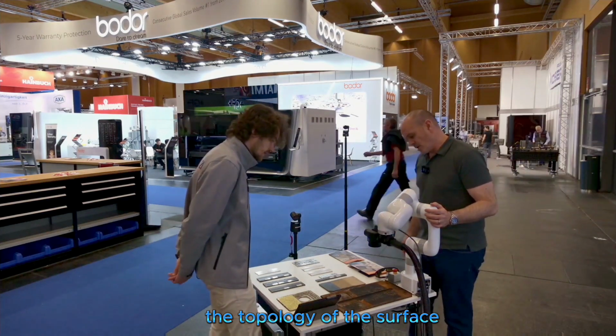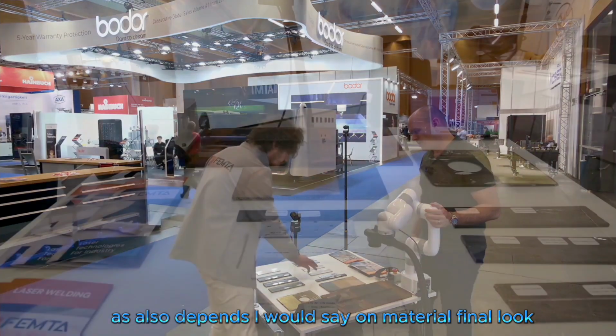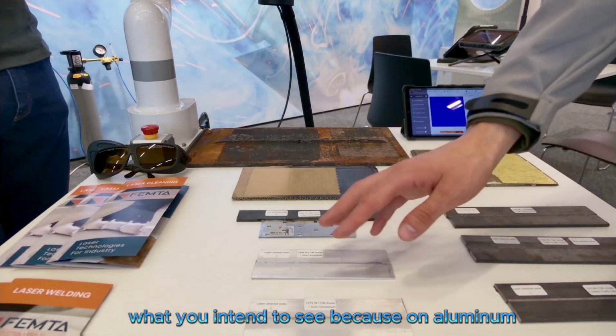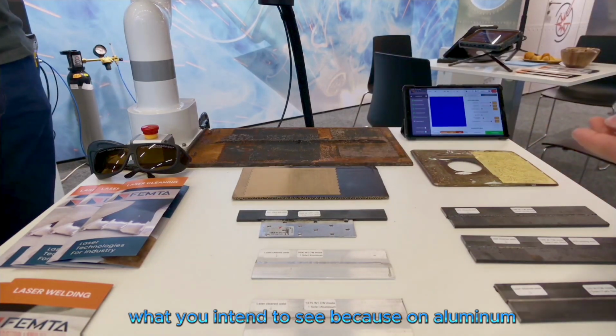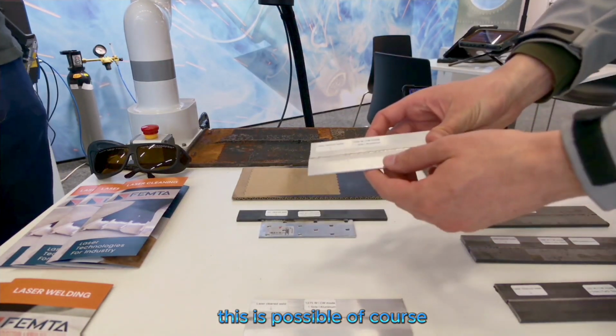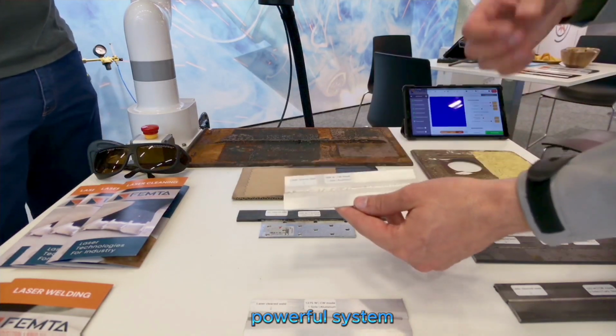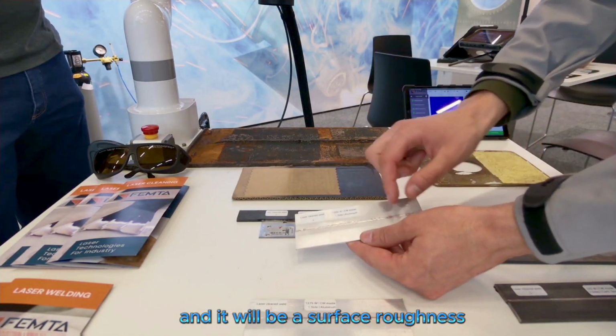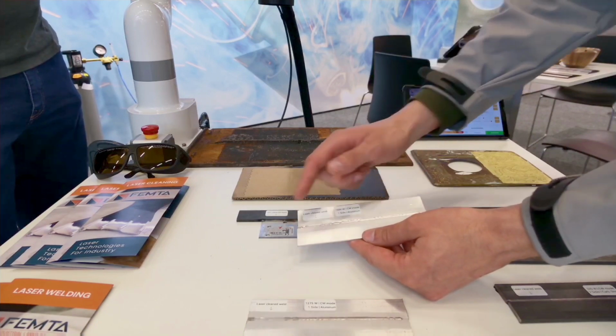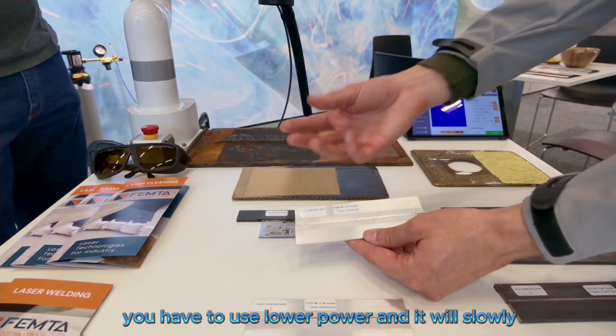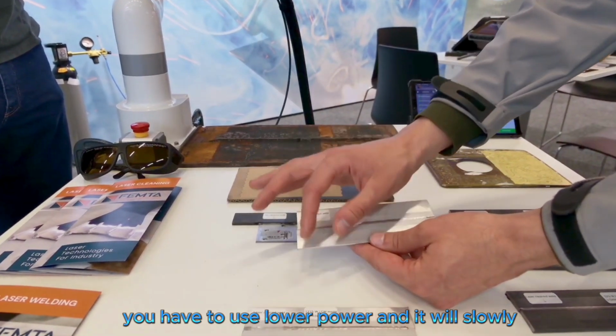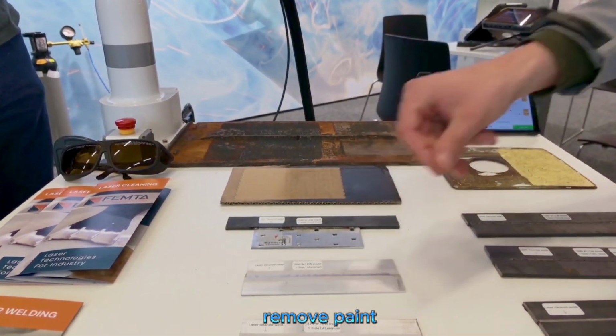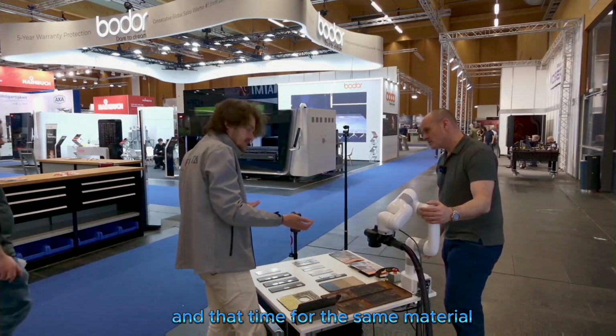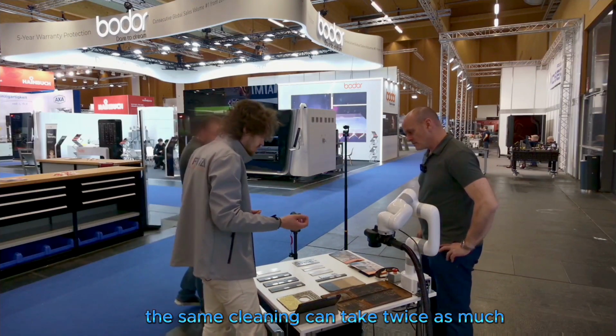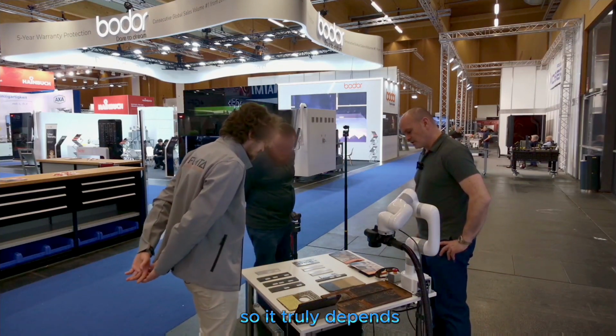And it also depends on the final look of the material, or what you intend to see. For aluminum, it will of course be much faster to use really strong power pulses, but there will be surface roughness, and it will not be that shiny. But maybe you have to preserve the shininess of the metal. You will have to use lower power, and it will slowly remove the paint compared to the higher power parameters. That time for the same material, same cleaning, can take twice as much. So it truly depends.